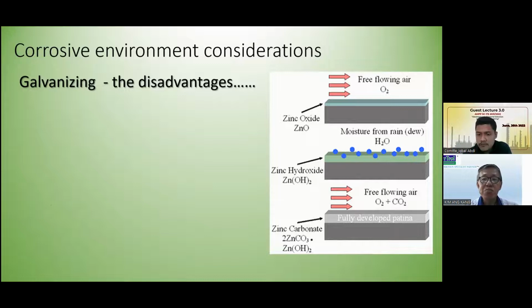So if we don't expose it to the air enough, typically when we have those galvanized zinc sheets come along and stack to each other and water gets in, after some time when we open up, we'll see white spots on the galvanized steel. Those are the typical white rust that happens on the galvanized steel.